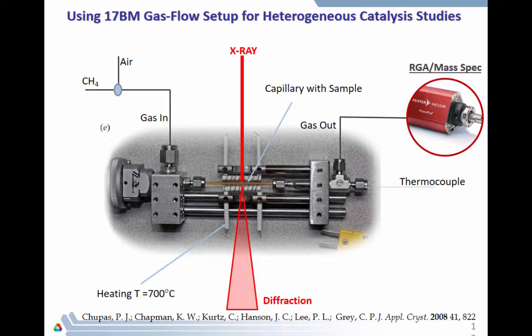you've got an excellent setup to study any heterogeneous catalysis system, because by shooting X-rays on your sample, you will be able to clearly see what structural changes happen with your material upon either a reduction or oxidation cycle. And at the same time, you will be able to easily track the products of the reaction being catalyzed with a mass spec.